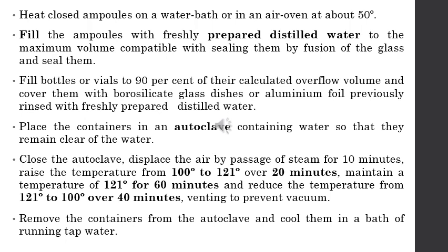Now, after this autoclaving, we have to maintain the temperature of 121 degrees for 60 minutes, and then reduce the temperature from 121 to 100 degrees over 40 minutes. After this is done, it has to be removed from the autoclave, cooled, and then kept under the running tap water.